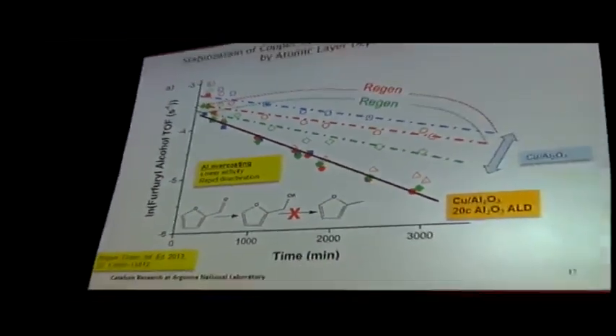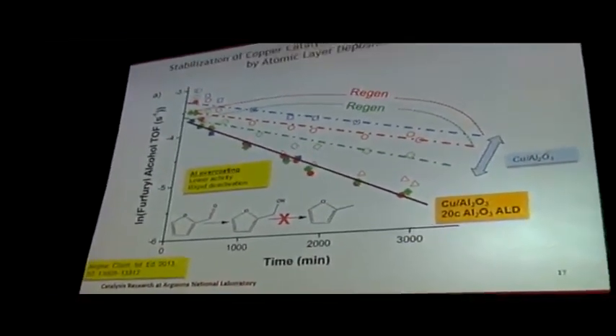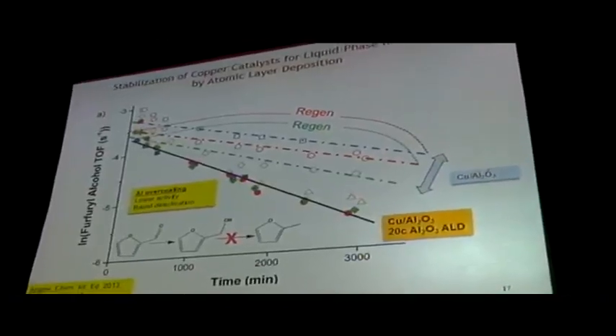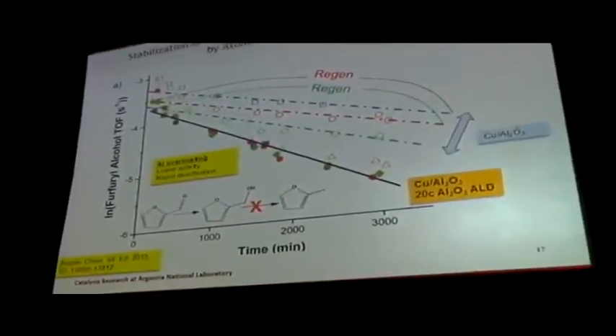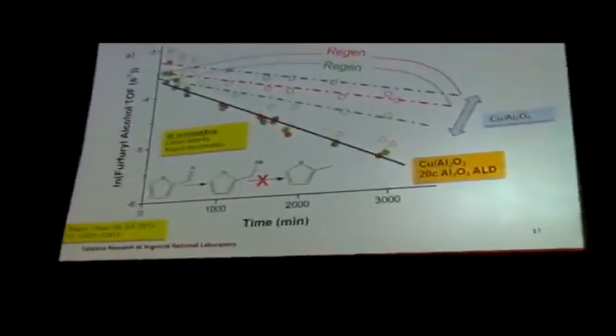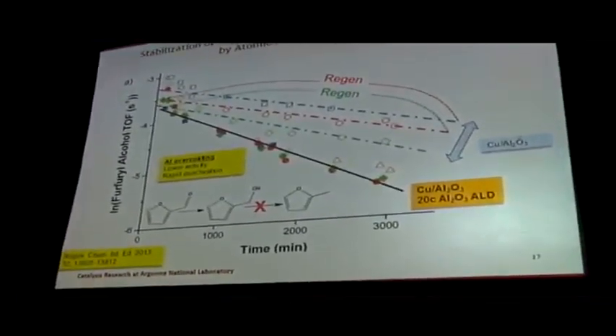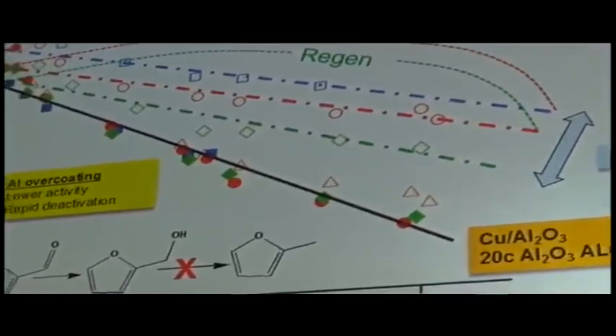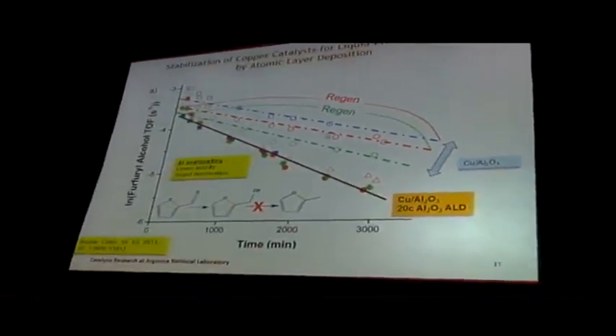When we first put in a reactor, this was work that was originally done at University of Wisconsin, one of our partners in the EFRC program there, and they saw the deactivation that you see going on in the top portion here. When it got to a certain time on stream, the material was regenerated and generated a new curve, which you see in the red here.